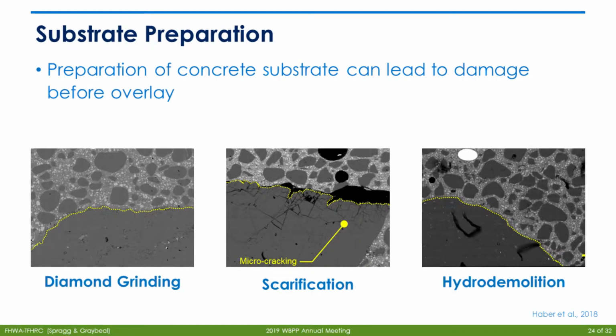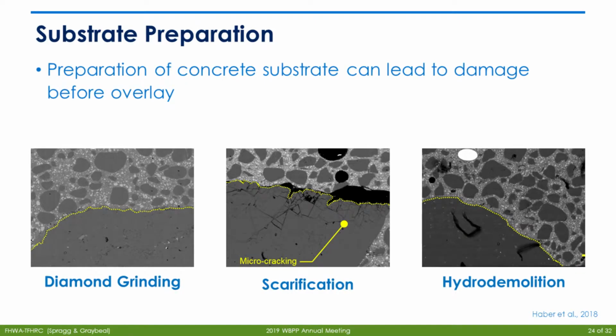And then looking at the substrate preparation, there was one particular pull-off data set that had a little bit lower bond strength. That was this preparation method here. So you can see the scarification method, in this particular application, kind of damaged the aggregates. So when we were pulling off our sample, it was already attached to a damaged substrate, which we think led to some of the premature failure. You can see diamond grinding does do some damage. I don't know if I've zoomed in far enough here on the photo, but this big gray piece is a piece of aggregate that does have some microcracking in it. That came from the diamond grinding process.